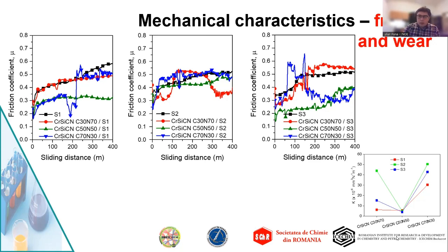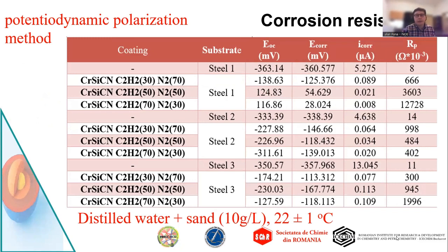Furthermore, we have evaluated the corrosion resistance of the coatings via the potentiodynamic polarization method, using distilled water and sand at room temperature. As a general remark, the coatings improve the corrosion resistance of the steel surface, which was expected. But all the layers deposited on the steel 1 substrate demonstrated the most electropositive value of the corrosion potential, indicating a relatively better corrosion resistance than S2 or S3.